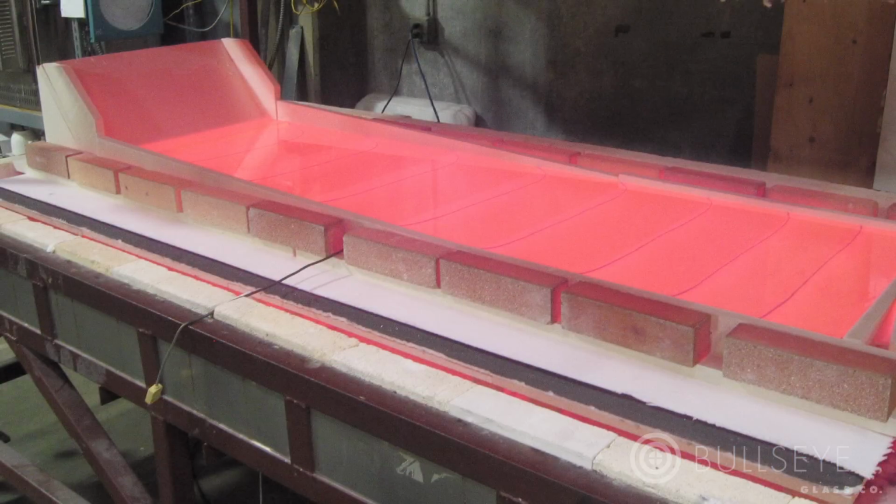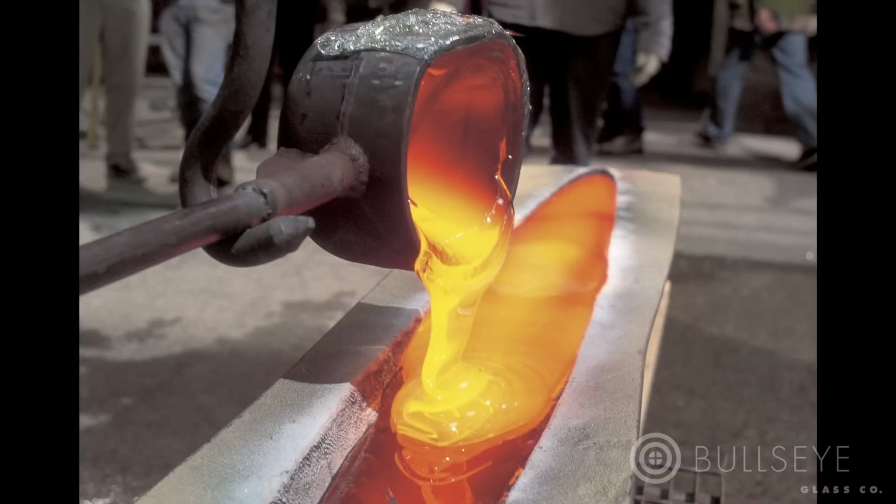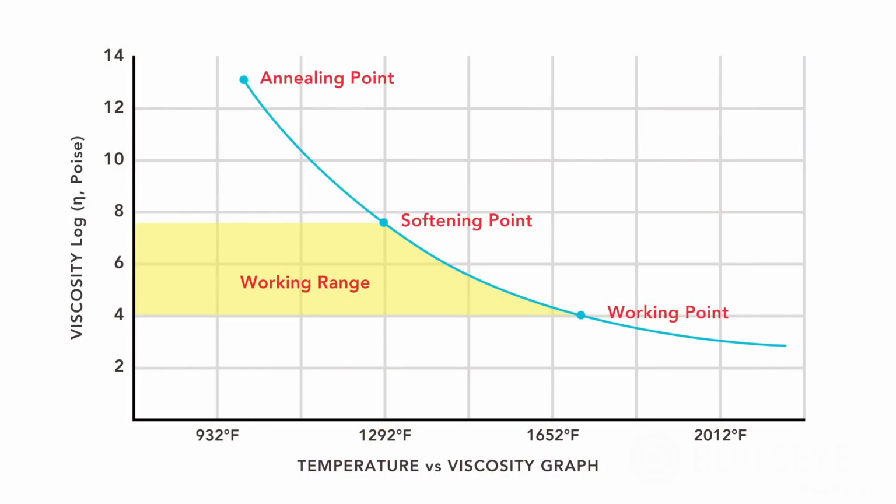It is this unique characteristic of glass that allows it to be blown or to be worked in the myriad ways we call kiln forming. As it is heated, glass gradually begins to behave more and more like a liquid until, at temperatures above 2000 degrees Fahrenheit, it will flow easily with a consistency similar to honey. The temperatures at which glass is worked in a kiln are usually between 1000 and 1700 degrees. Within this range, a wide variety of effects may be achieved by using a variety of processes.